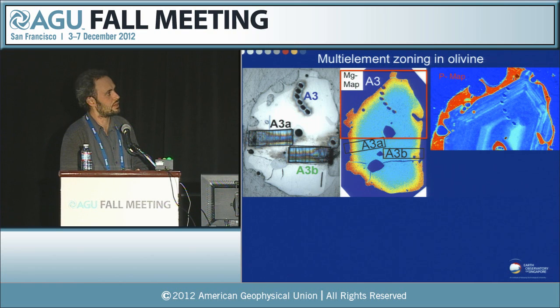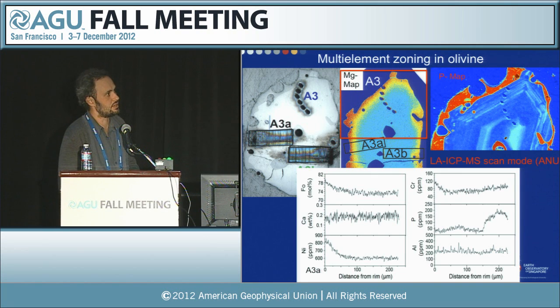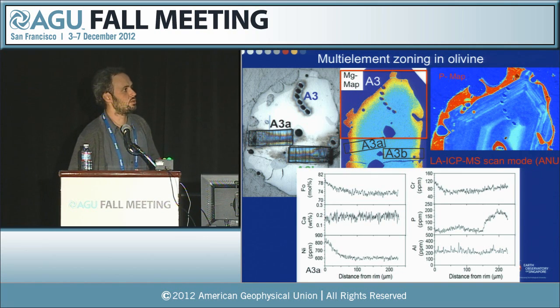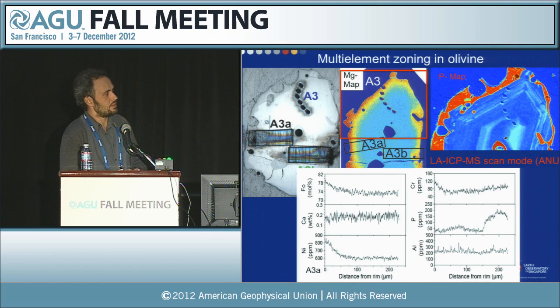So here we have our olivine crystal. This is a reflected image, this is a magnesium map, and as you see here, you can contrast the difference in features if you look at the phosphorus versus the magnesium. What we did here is we used a laser in scan mode, this is at ANU, and here you see the scans. We use the laser and continuously scan, and you get these profiles: forsterite, calcium, nickel, chromium, phosphorus, and aluminium.